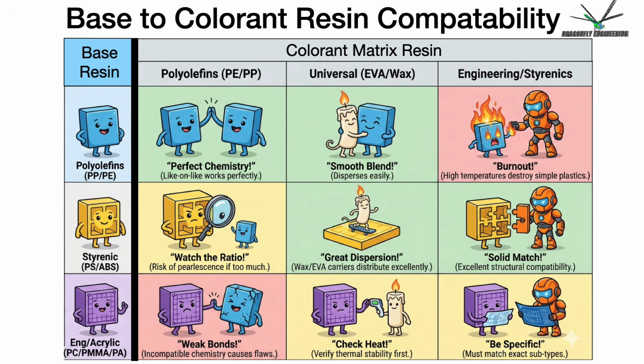The styrenics are kind of interesting, and they offer a more flexible mid-ground chemistry. The styrenic base resins show the highest tolerance for different carriers, and they only drop to situational for polyolefin and engineering options. So there are clear material hazards and performance risks whenever crossing incompatible chemistries that can trigger severe material degradation. Some of those risks include destroyed optical clarity and reduced impact strength in acrylic. Other mismatches cause severe mixing issues or structural weakness or thermal degradation. So those are things to watch out for.